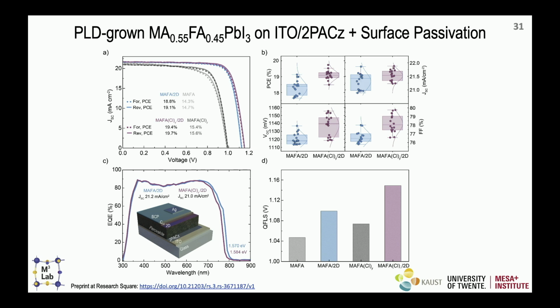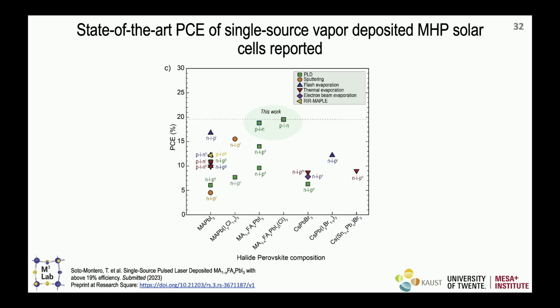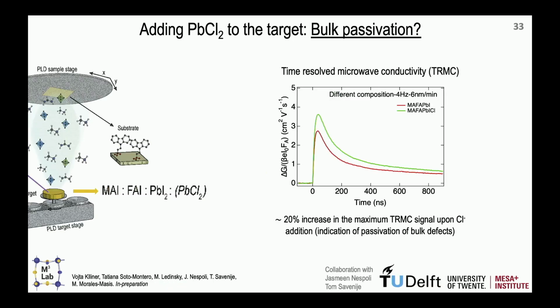So that was a very critical demonstration, because now we can say PLD actually can produce films that can give a good solar cell efficiency, which is something that when you work on halide perovskites is a question I was getting all the time. I was not planning to go so much into devices, but it was a critical step for the field to show we have to do it. And in terms of state of the art, we look at just single source vapor deposition. Basically, this is the highest reported efficiency, getting very close to 19.7%, very close to 20, if you add this passivation. So for us, it was a very exciting step. We are still waiting for a paper to be accepted, hopefully soon.